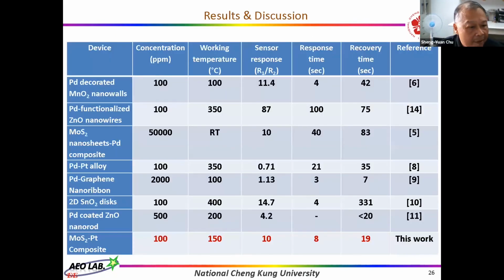Here is the comparison of our work with other published data. We can see the sensor concentration detection is about 100 ppm, and the working temperature is 150, and the sensor response can be up to 10, and the response time is 8 seconds, and the recovery time is 19 seconds. And compared with other published data, I think these data are good enough.